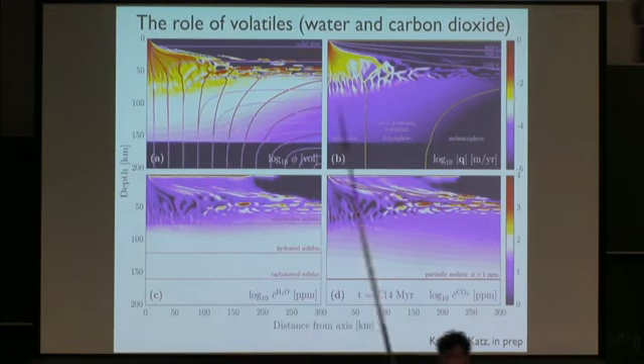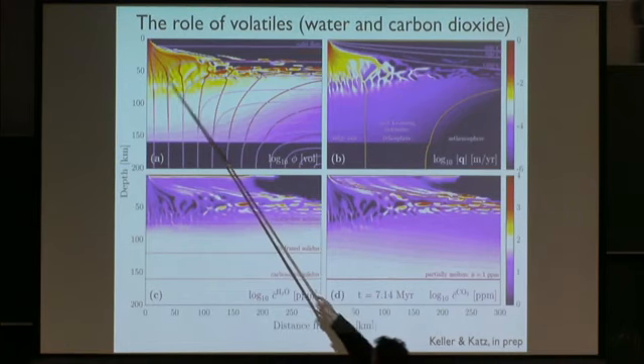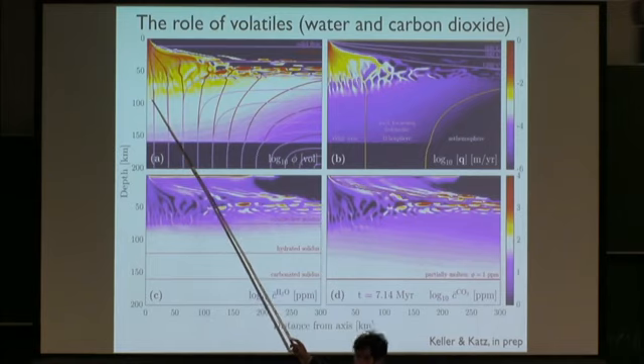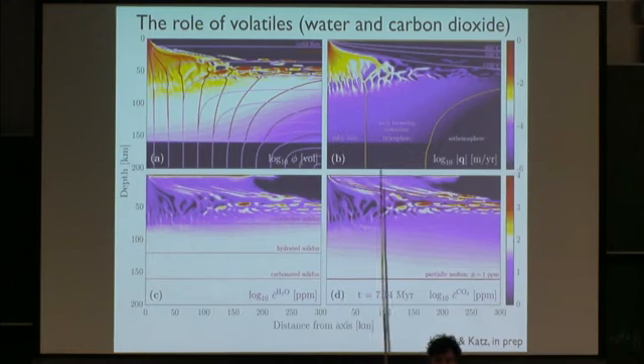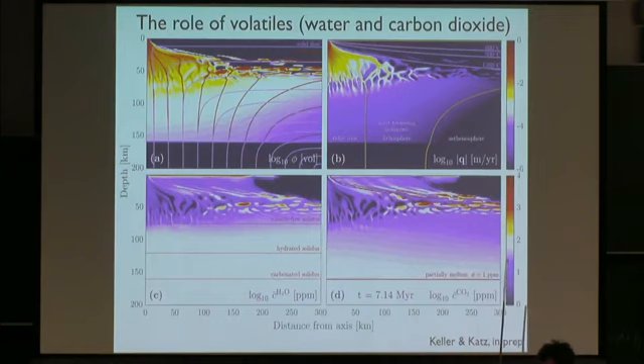Roughly the maximum degree of melting on the axis. I think, gosh, I don't know. Toby, is it? I didn't understand the question. What is the maximum degree of melting? So the extent to which a parcel of solid has melted when it's gone from here to here. By this point, it's only 1%-ish. It will be of the order of about 15%, I think. 15%, yeah. So as usual, with this fictitious phase diagram, one is loath to pin too much significance on any one number, but we try to come within observational constraints, though we don't try extremely hard. If you wanted it to be 20%, it could be 20%, but it would just be a trade-off in some other parameter. I'm just trying to get some rough rules of thumb.